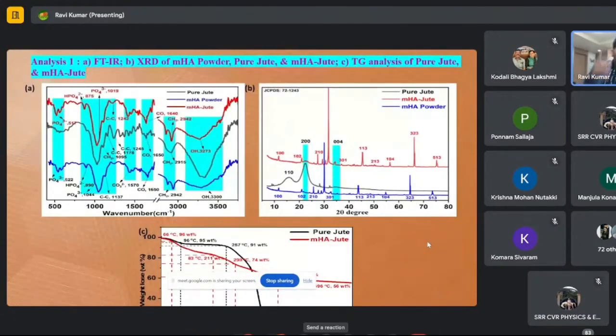So we analyzed the material to see whether it really meets our parameters or not. We studied that with FTIR, and we can also see the phosphate groups on the surface. It means that if phosphate is there, automatically mHA is deposited on the surface. There are also CH2 groups and OH groups coming from the cellulose surface.